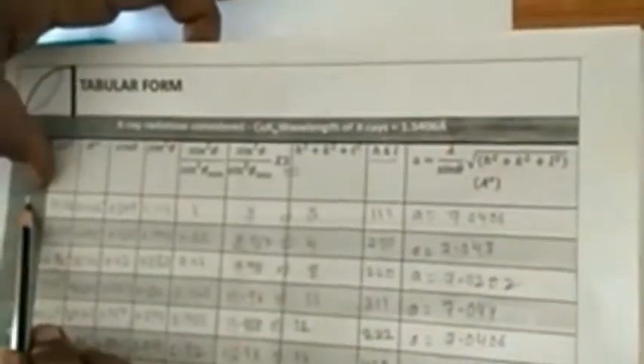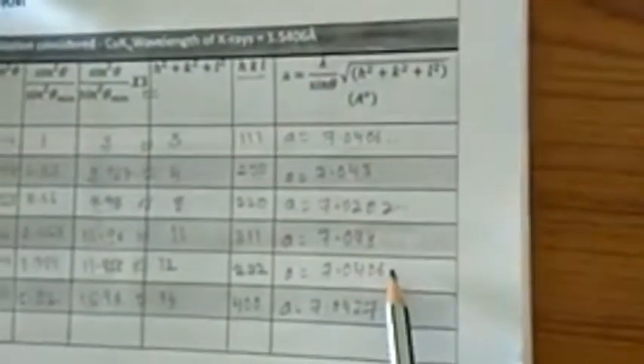Right. Now, we can find the lattice constant. The formula is given as a equal to lambda by sine theta into root over h square plus k square plus l square. For each and every Bragg diffraction peak, we find the corresponding lattice constant. On substituting the value of sine theta and h square plus k square plus l square for the first Bragg diffraction peak, we got 7.0406. For the second peak, we obtained in a similar fashion 7.043. For the third peak, the calculated lattice constant is 7.0282. From the fourth peak, it is 7.044. From the fifth peak, it is 7.0406. And for the final diffraction peak, it is 7.0427. Now the average lattice constant of the crystalline material can be calculated to be around 7.04. This is the average lattice constant of the material.